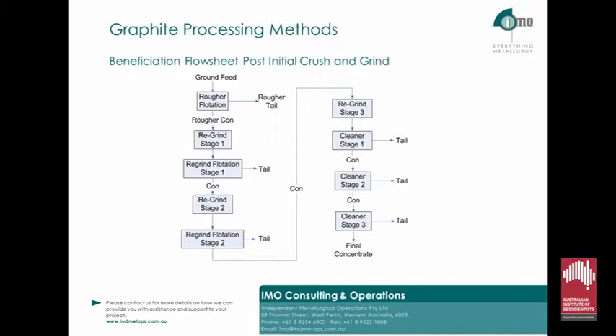The beneficiation flow sheet is generally broken up into multiple stages of flotation and regrinding in order to achieve a final concentrate. The initial flotation stage is termed the rougher stage. The subsequent regrind stages are numbered to clarify their position in the flow sheet. The flotation stage after the regrind is termed the regrind flotation stage, and the stages after the final regrind stage are termed the cleaner stage.